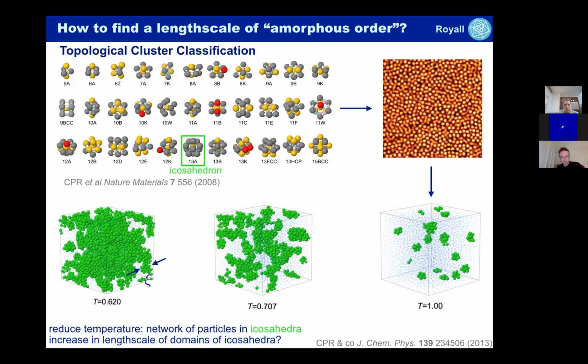So the icosahedra are shown in green, the other particles in the liquid are little blue dots, and as we drop the temperature, we have a large increase in the number of icosahedra. There is also some kind of a structural length scale emerging in the liquid that I've noted here as Xi. So the first observation here is this looks quite good because we have the emergence of a network of icosahedra as we drop the temperature.